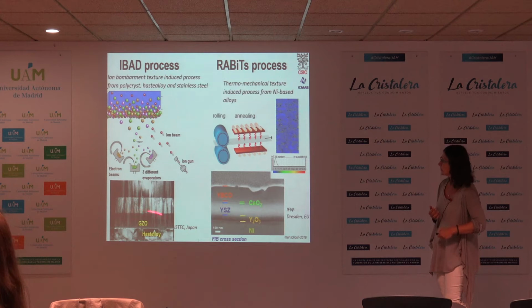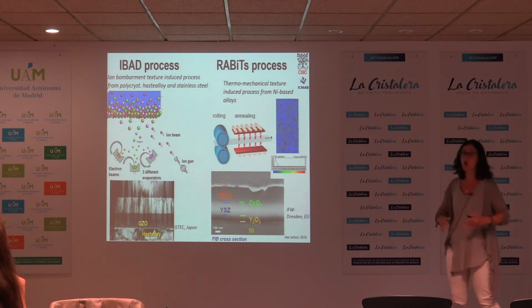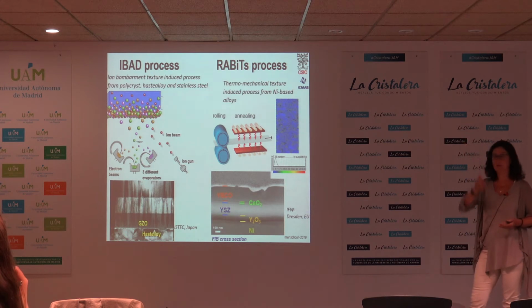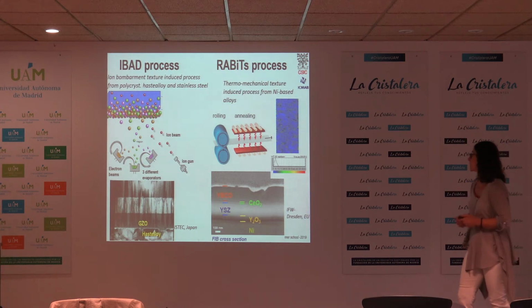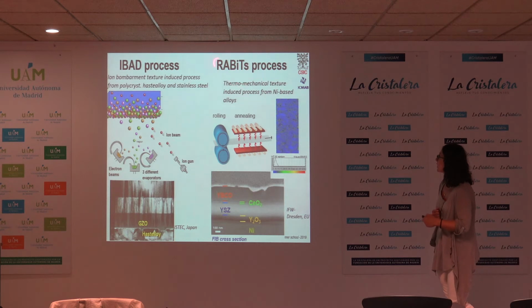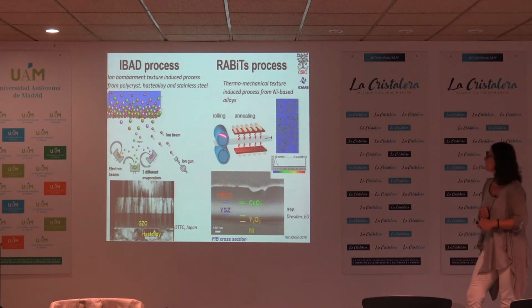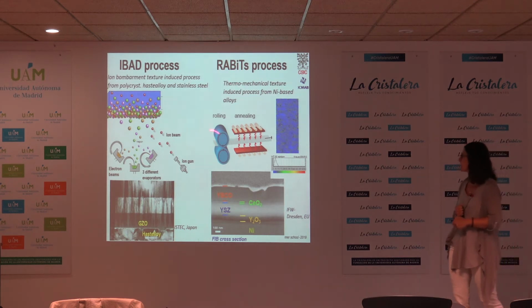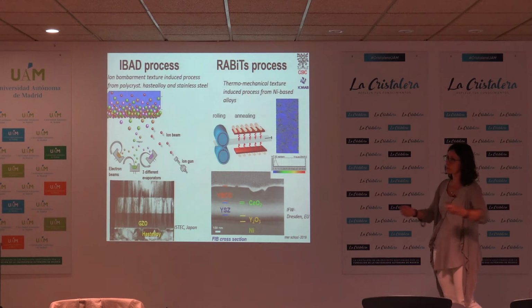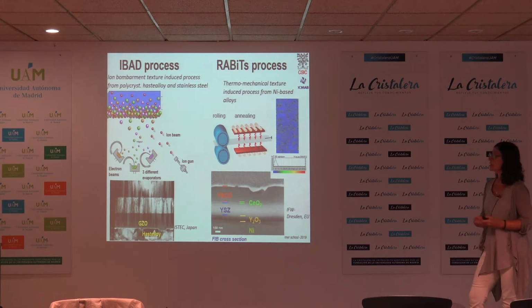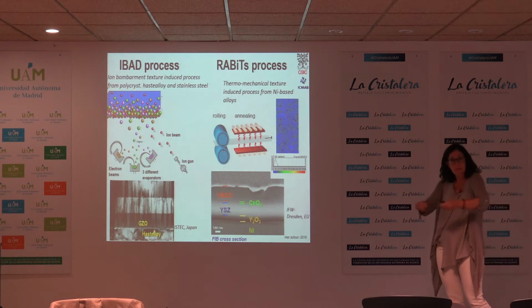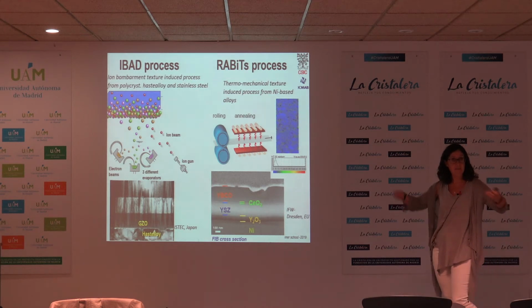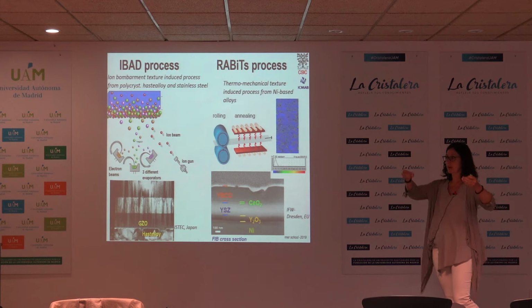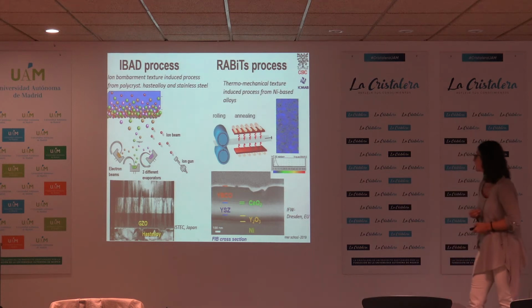And then on top of this epitaxial layer, you have to grow the other buffer layers and the YBCO, all things epitaxial, okay, with good lattice match. The other possibility is what is called RABiTS, which means that you start with a nickel or nickel-based material and do a thermomechanical process of rolling and annealing, so that at the end the nickel will be textured, and then on top of this nickel you have to put the buffer layers and then the superconductor.